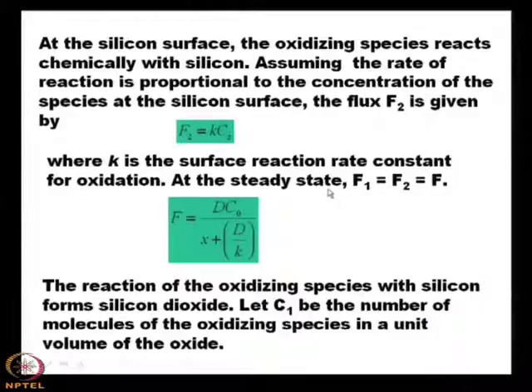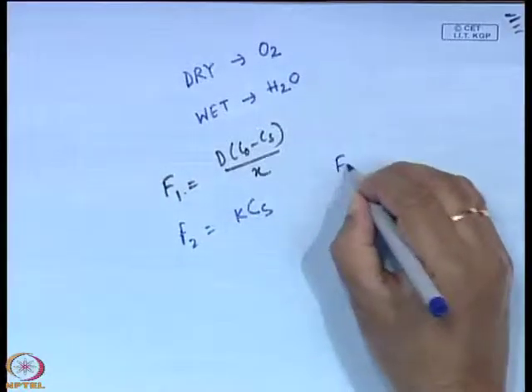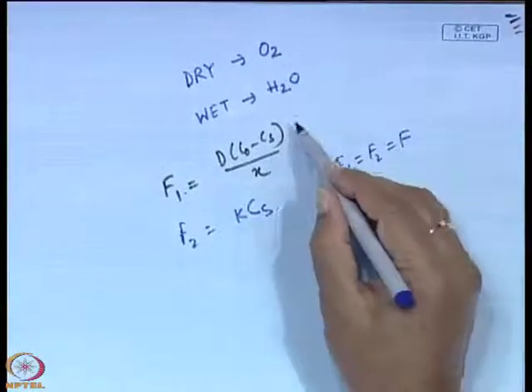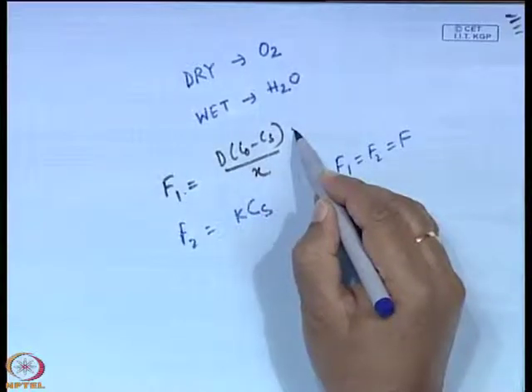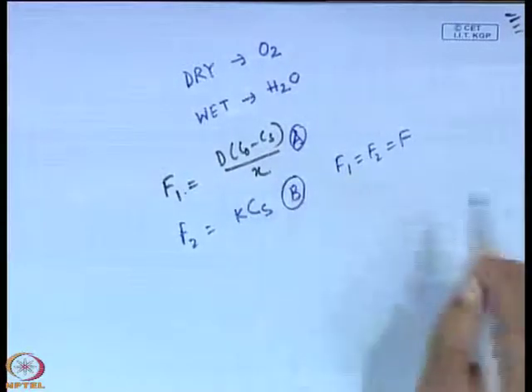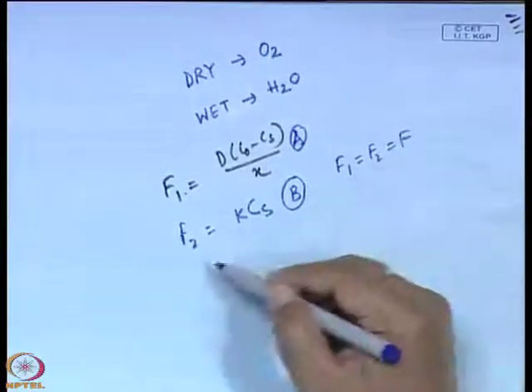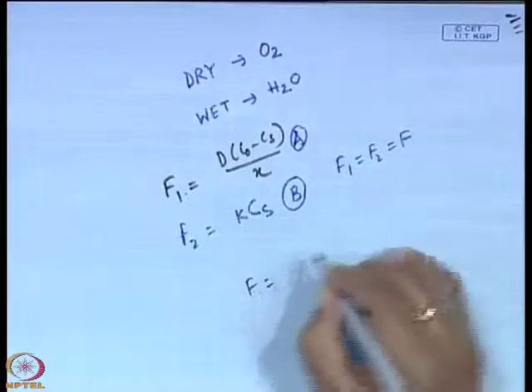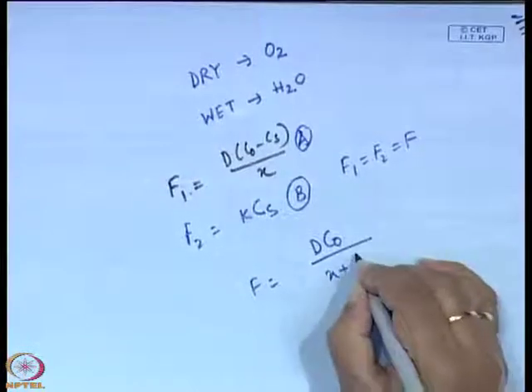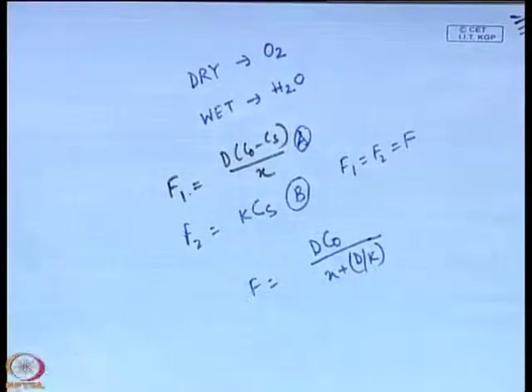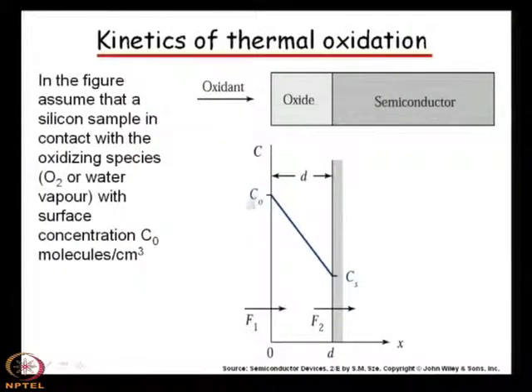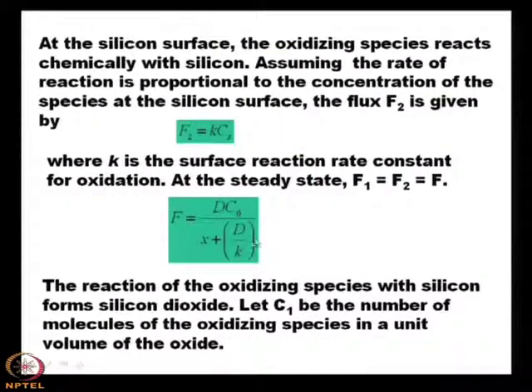At the steady state, F1 and F2 will be equal, so F1 equals F2 equals F. Now, if you equate these equations, suppose this is A and this is B, and put the value of Cs in terms of F, then we find that F becomes D C0 by x plus D upon k. So, C0 is the initial surface concentration of the oxidizing species, and D is the diffusion coefficient or diffusivity. The reaction of the oxidizing species with silicon forms silicon dioxide. Let C1 be the number of molecules of the oxidizing species in a unit volume of the oxide.